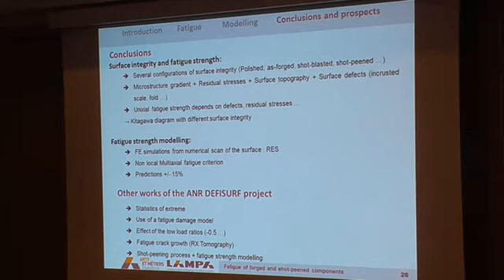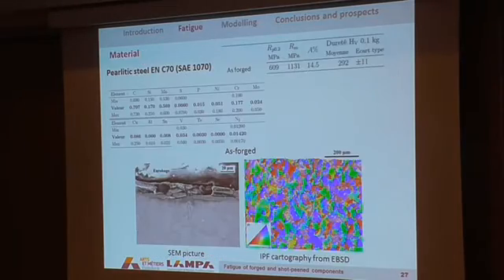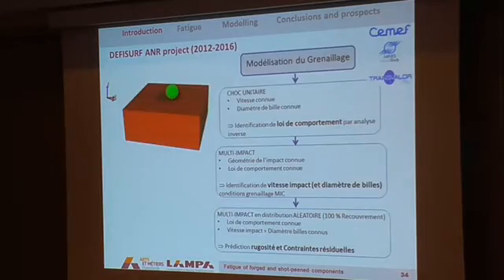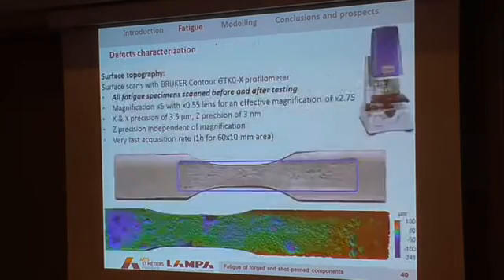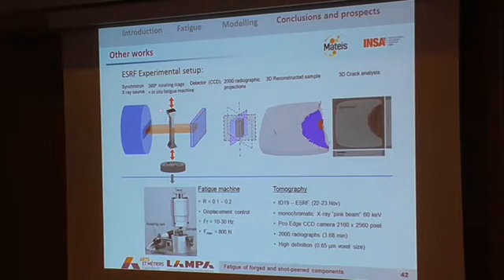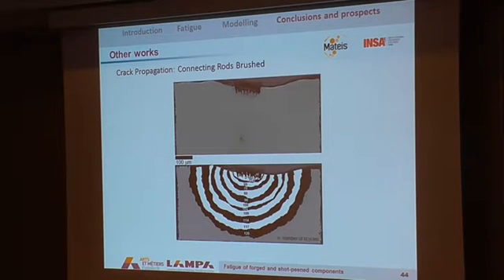We did many other works in this project, like studies about the crack growth at the synchrotron, using, once again, some specimens machined from the connecting rod. And what you see on this picture is the crack growing from a defect we introduced at the specimen surface. The same here for the shot blasted.